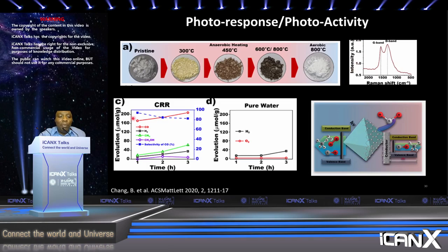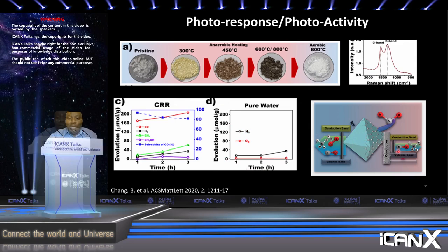And then the final thing that we did, and this was in collaboration with Professor Jinlong Gong from Tianjin, we did a carbon reduction reaction, and we found out that these materials were very selective in the reduction of CO2 to CO, and we never saw any water splitting, or the water splitting was insignificant, which in combination with UV-Vis, we can confirm that actually the material had changed its band gap, and now it was a mixed band gap material with a band gap as low as 3.2.